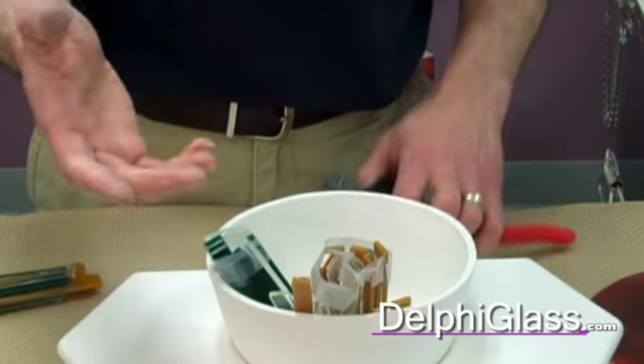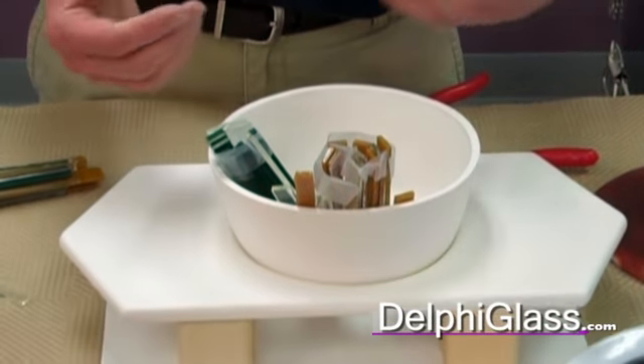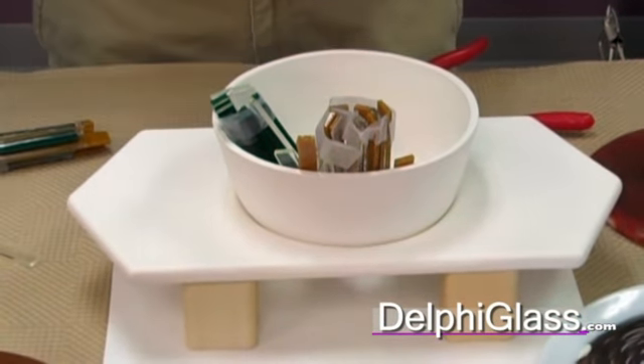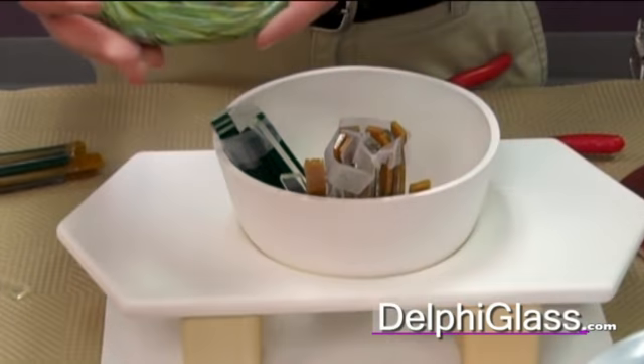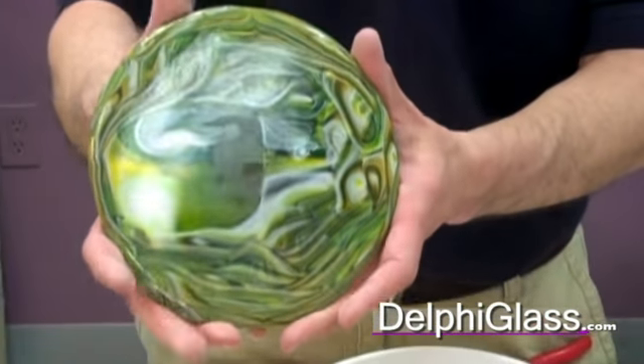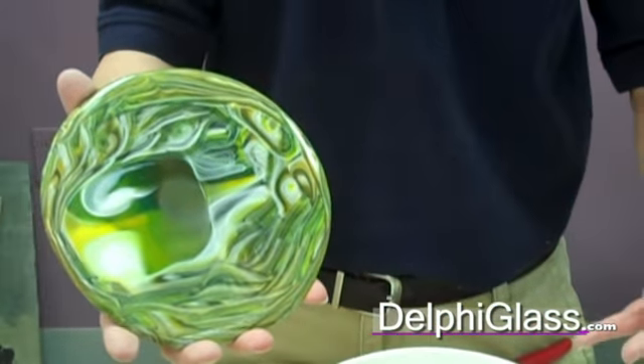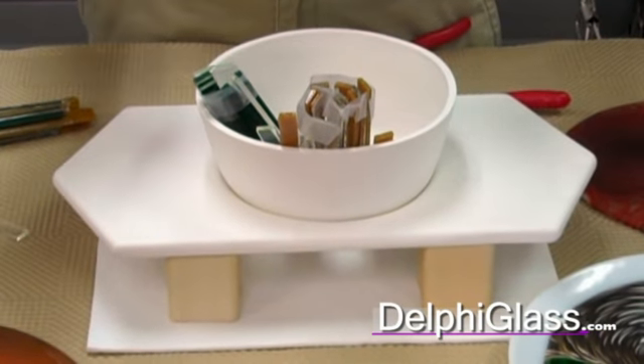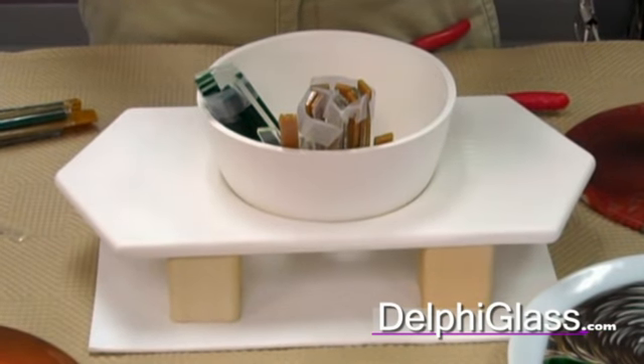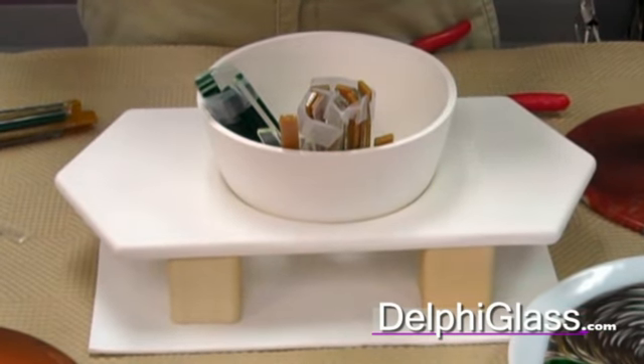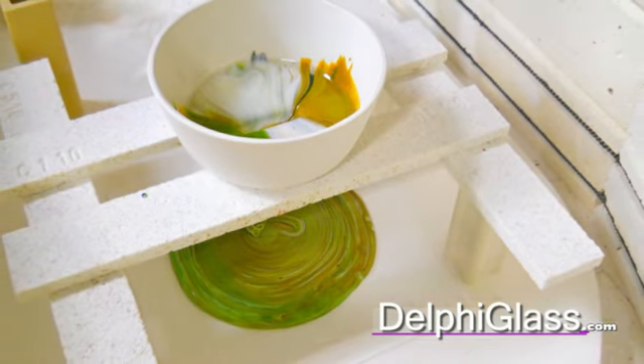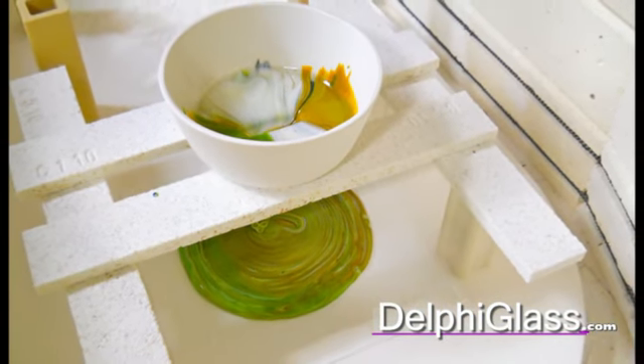A question we get asked a lot is, how much glass do you need to put in the pot? I can tell you that this particular piece is about a 6.5-inch circle, and I put in 2 pounds of glass. One of the keys to reusing these pots is to try to get out as much of the glass from inside the pot as you can, and that totally has to do with the firing schedule. When I'm firing these, we're going to take these up to about 1600 degrees.